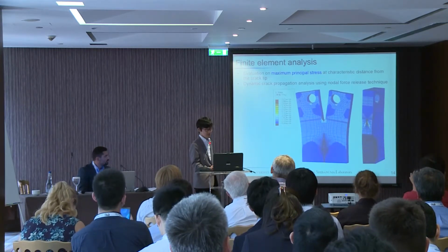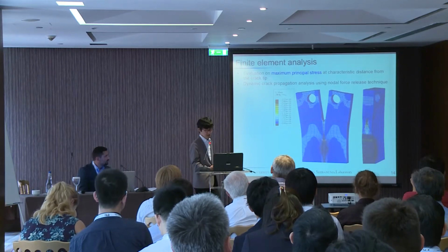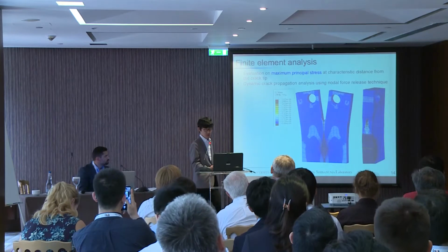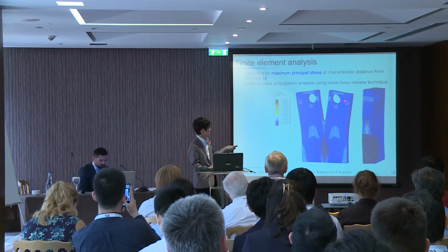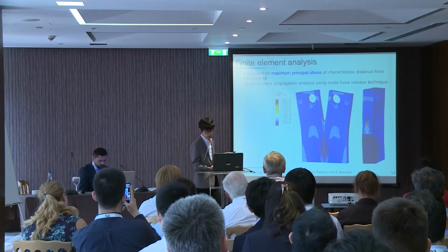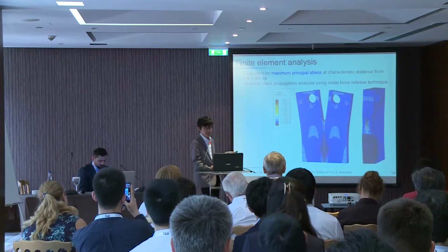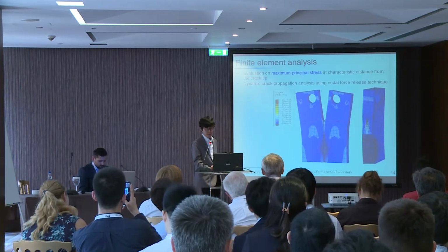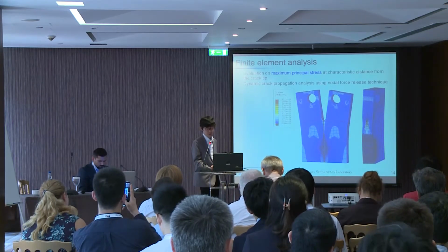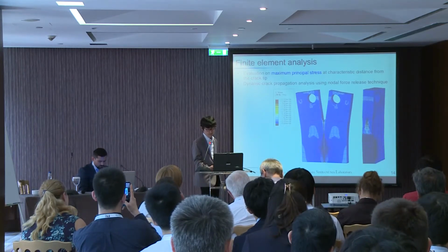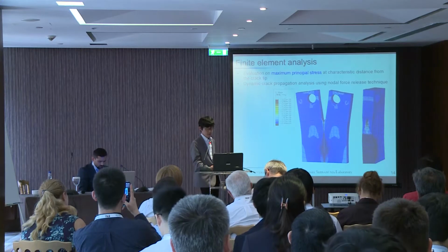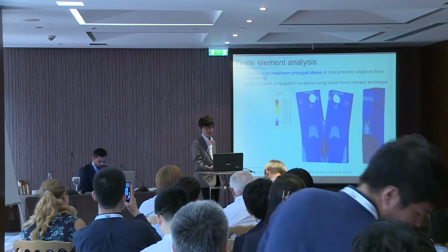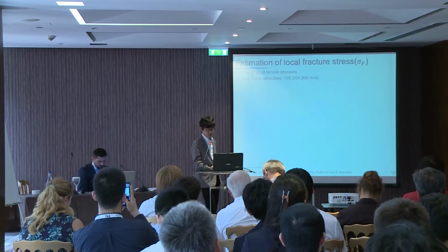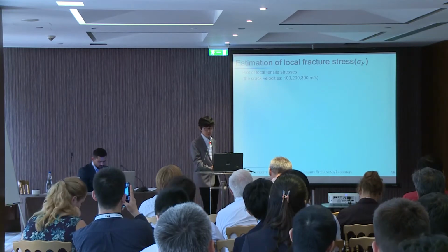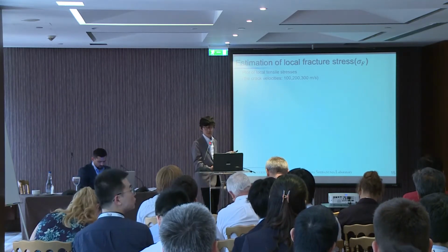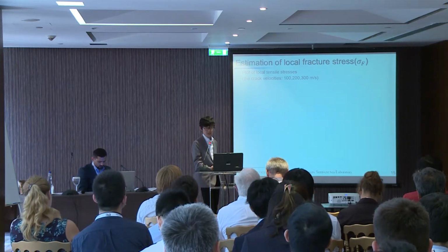This movie shows finite element analysis results. At first, pin force displacement was imposed to rigid pin until displacement reached experimental results. And once it reached experimental results, crack propagation started. In this movie, we assumed the crack velocity 300 meters per second. The crack velocity just before the crack arrest is considered to be from 100 to 300 meters per second at low temperature.